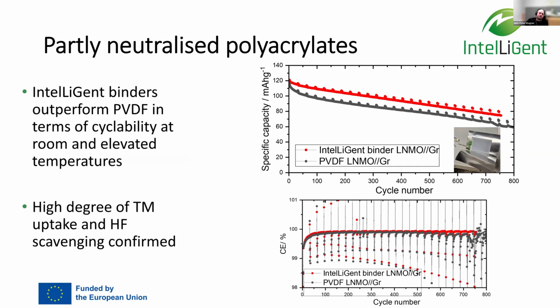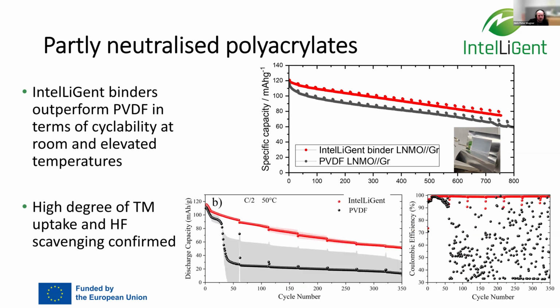Here's an example from single layer pouch cells of our LNMO material with our binders compared to PVDF baseline. Also, everything in LNMO graphite setup. And we get higher capacity and better retention, higher Coulombic efficiencies, and we could also measure high degrees of transition metal uptake by the binder, and not only transition metal, but also HF scavenging effects. That really makes a difference in cycle life, especially if we look at the whole thing at 50 degrees, where we all know that LNMO has massive problems, that we can really outperform PVDF-based electrodes here. So that was the first example I wanted to share with you.